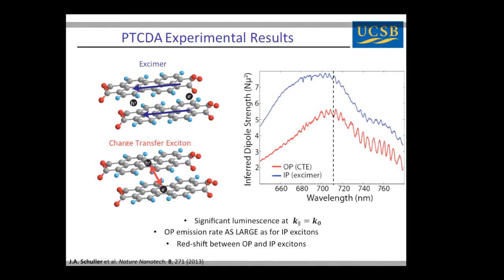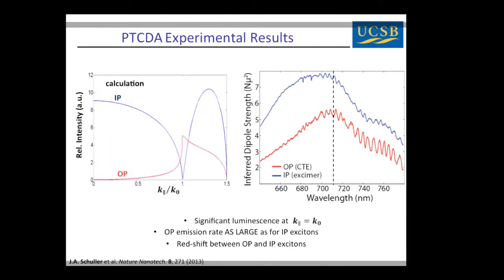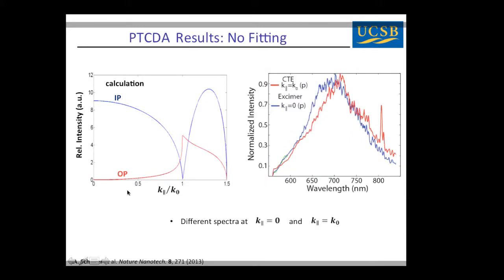Okay? Now this comes from fits, so one might have a bit of skepticism. Turns out our life in this particular case is made easier by the fact that we have this unique behavior at the critical angle where the light from our in-plane dipoles goes to 0. So if I make a measurement over here, at normal incidence, I only see light coming from my in-plane oriented dipoles. And over here, I only see light coming from my out-of-plane dipoles. Okay? So rather than measuring across the whole Fourier space or whole backfocal plane, we can actually just make two measurements. Okay? And now, without any kind of fitting, we see the same frequency shifts that I showed you before.